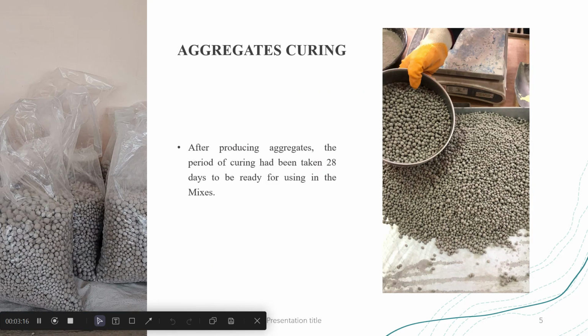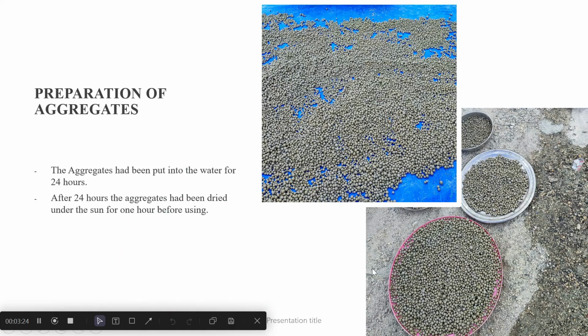After producing the aggregate, the curing period was 28 days to be ready for using in the mixes. Before casting the concrete, before using this aggregate, the aggregate had been put into the water for 24 hours. After 24 hours, the aggregates had been dried under the sun for 1 hour before using.